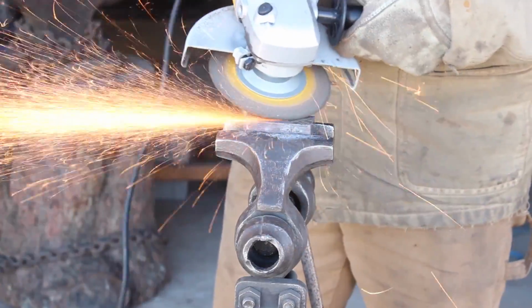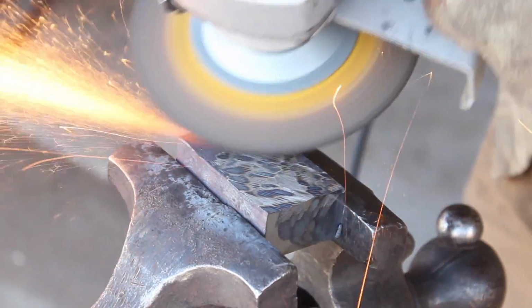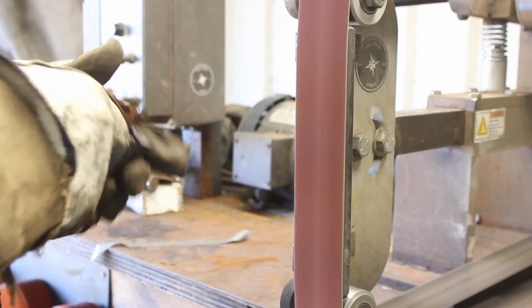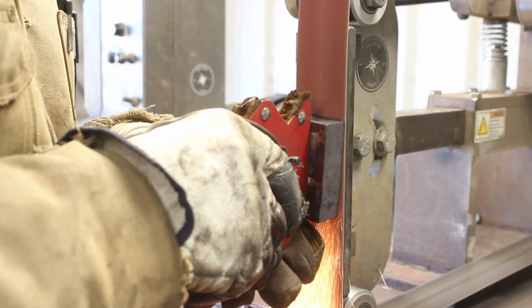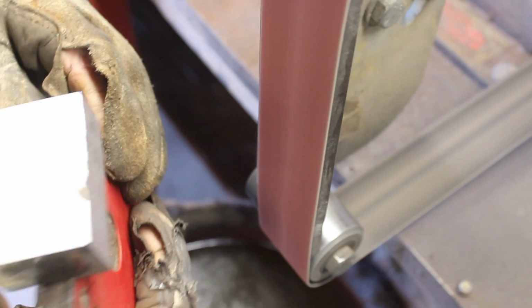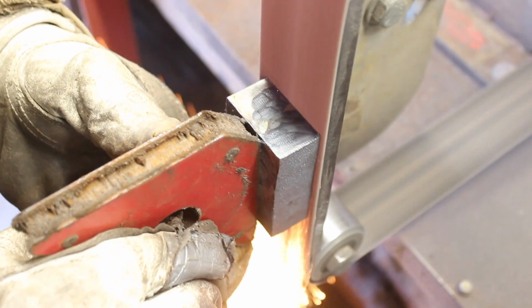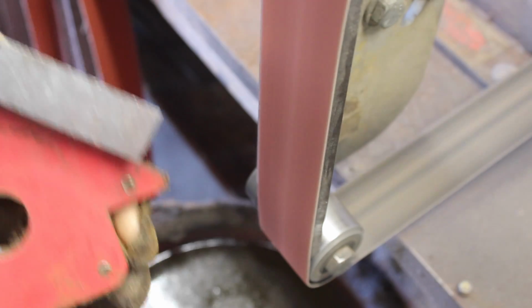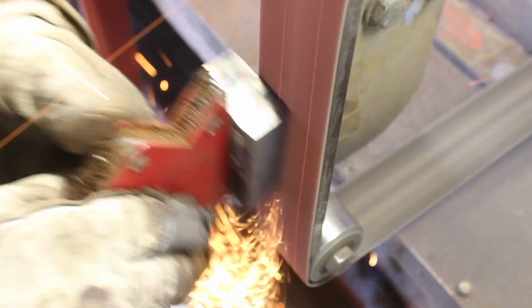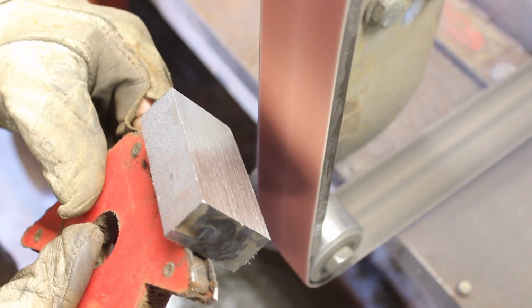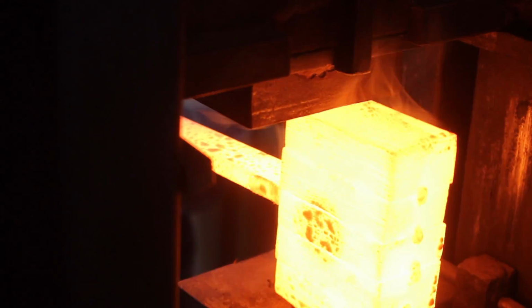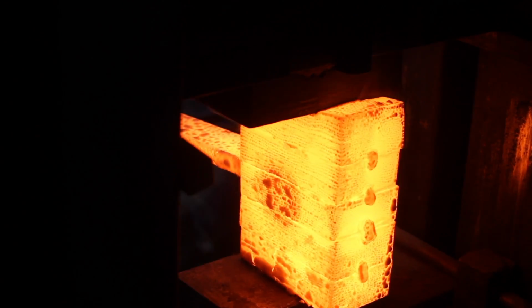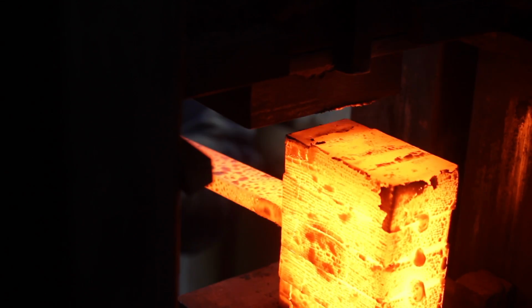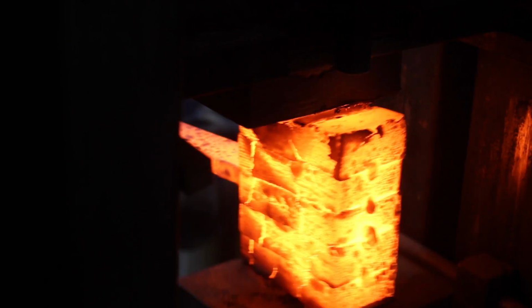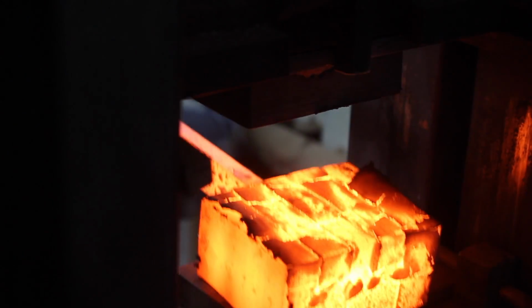So once again, we do have to clean off all the surfaces that are going to be forge welded together again. I'm starting with the angle grinder because this forge scale is extremely destructive to even high quality grinding belts. So once that's cleaned off, we can go to the grinder and give ourselves a nice flat, clean surface to mate to the next piece of steel. So repeating the processes that you just saw, we'll go ahead and forge weld this together again. And again, I'm working from back to front to give the opportunity for any flux or impurities to squeeze out from between the layers and bring that steel together into one solid piece.